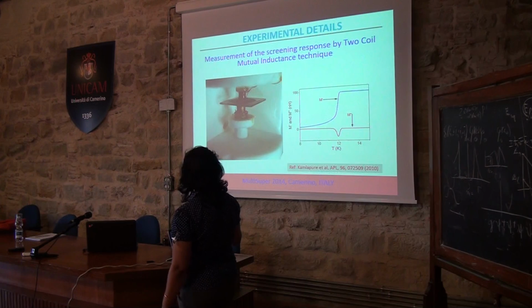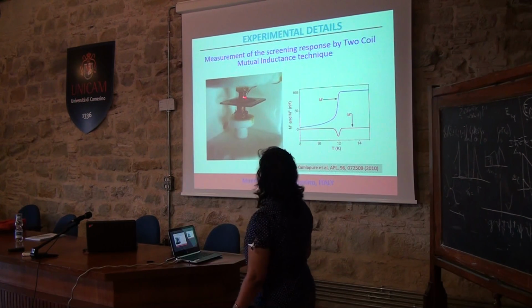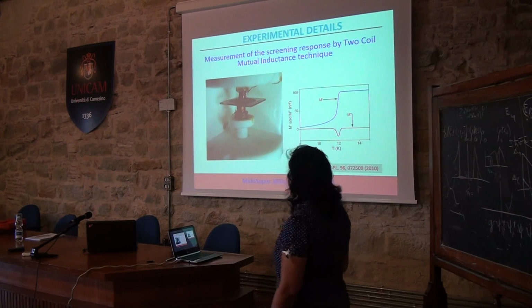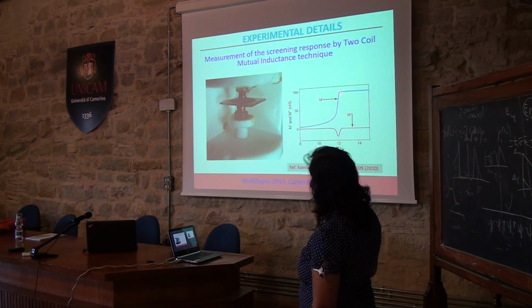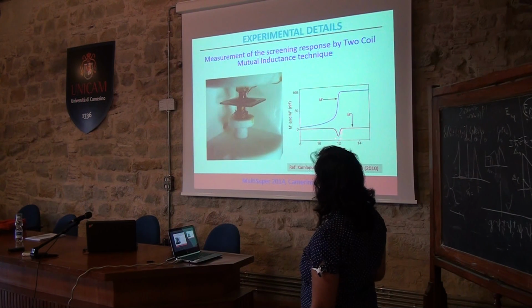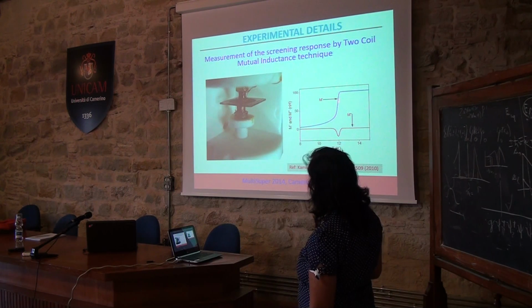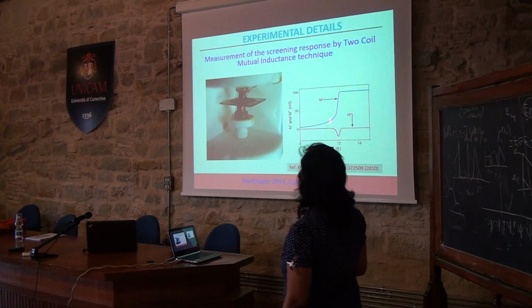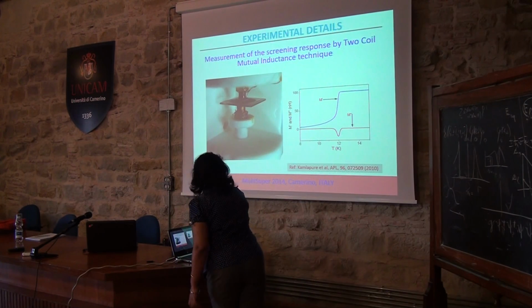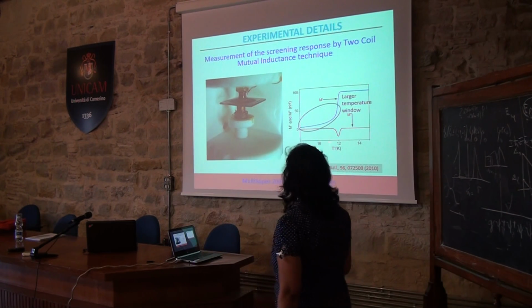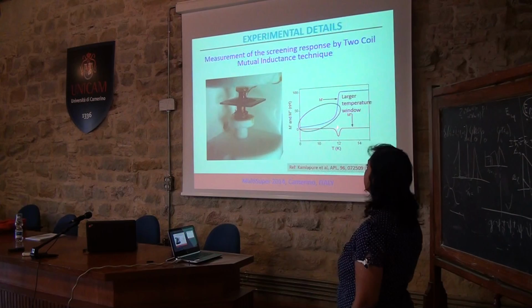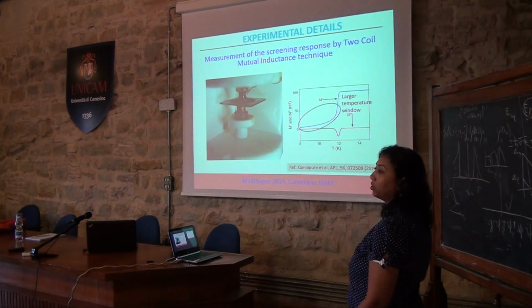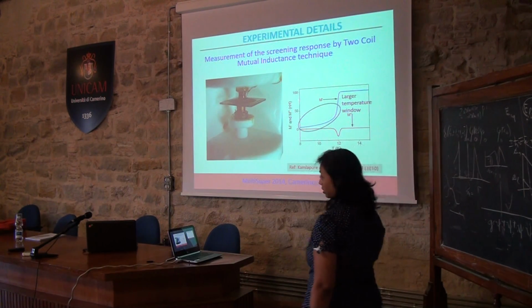This is just a picture of the probe which we use. What we see is that this is the real part of the mutual inductance and this is the imaginary part. You see that as soon as the film becomes superconducting, you have a drop in the mutual inductance signal. And now you can see that here we have sufficient signal to see what is happening to the matching effects deep in the superconducting state.